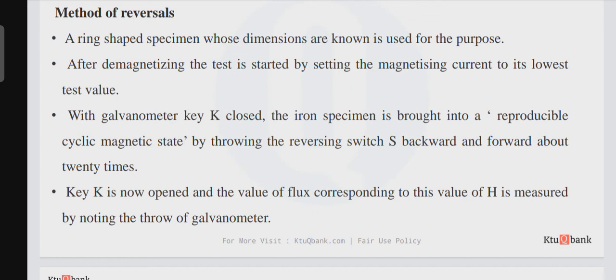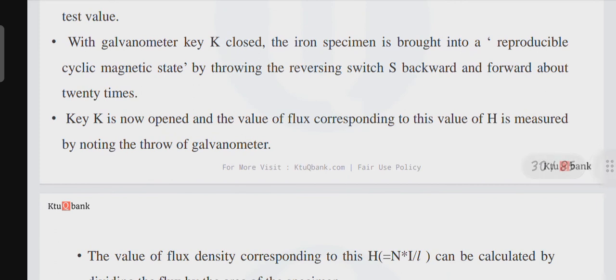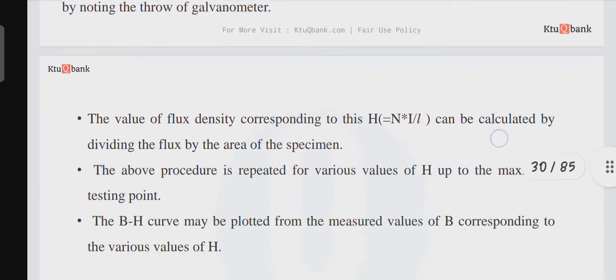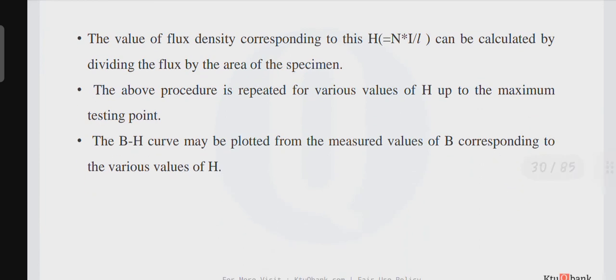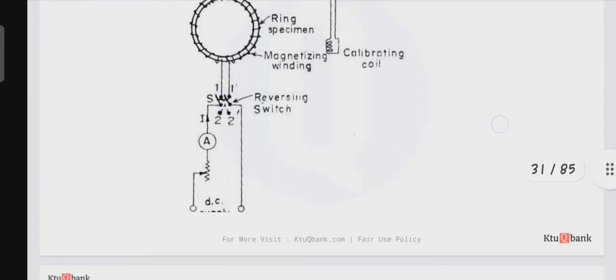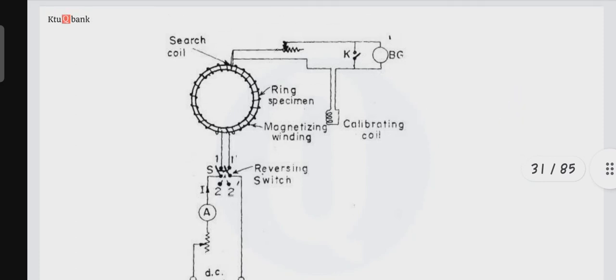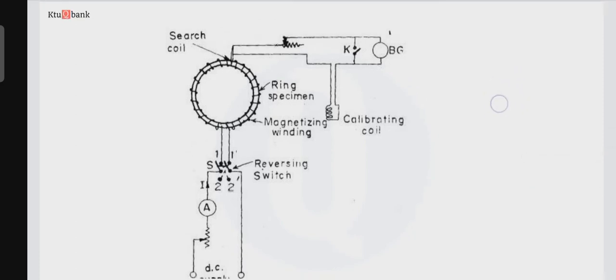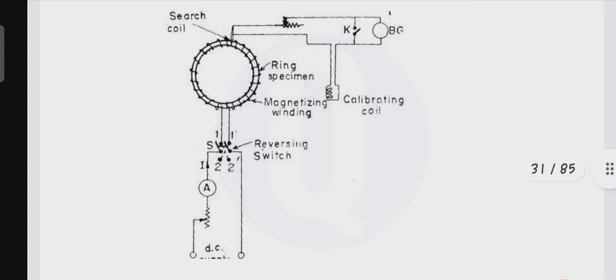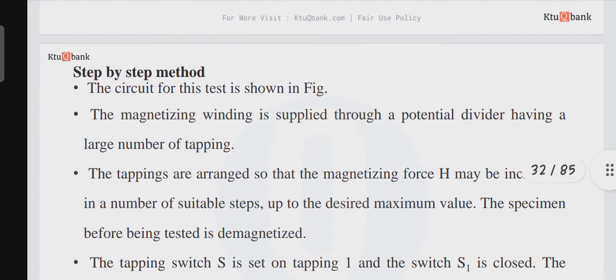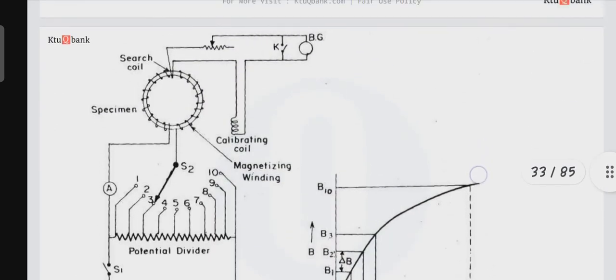Key K is now opened and the value of flux corresponding to this value of H is measured by noting the throw of galvanometer. The value of flux density corresponding to this H is equal to N times I by L, and can be calculated by dividing the flux by the area of specimen. The above procedure is repeated for various values of H up to maximum testing point. The BH curve may be plotted from the measured values of B corresponding to the various values of H. This is the method of reversal diagram: reversing switch, magnetizing winding, ring specimen, search coil, calibrating coil. Then step-by-step method. This is the figure of step-by-step method.